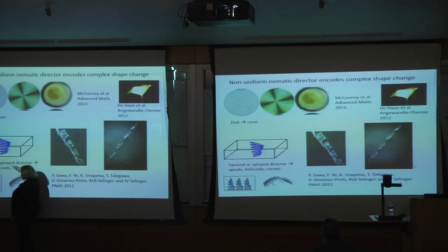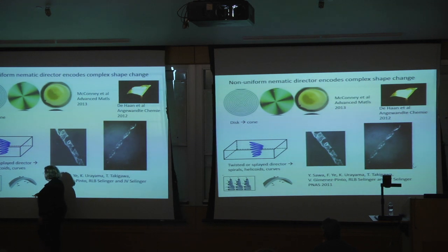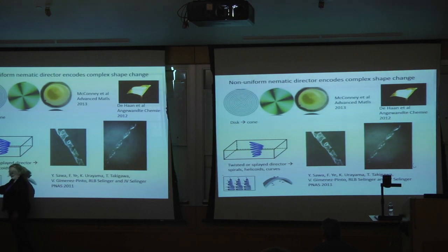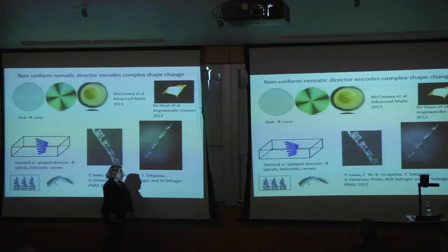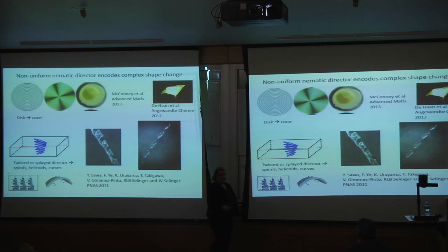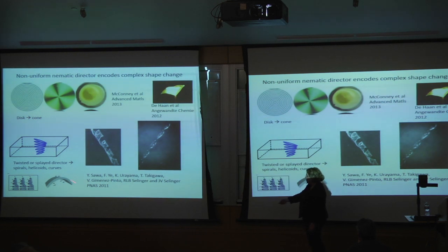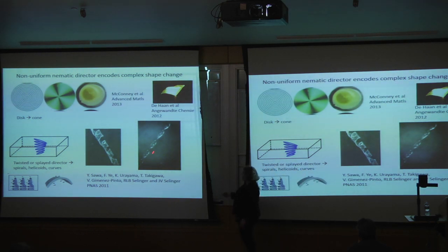We can also put a splay pattern in, where on the bottom, the nematic liquid crystal is parallel to the bottom of the substrate, and vertical on the top. All of those things program different types of deformation. In this case, you could get a bend, and in this case, you can get a twist. If the ribbon is narrow, you get something that looks kind of like a rotini noodle. If it's wide, you get something that looks more like a paper towel roll that's been unwrapped.